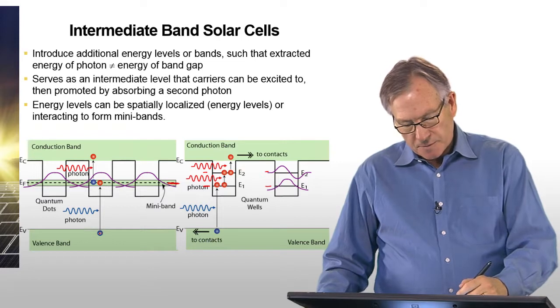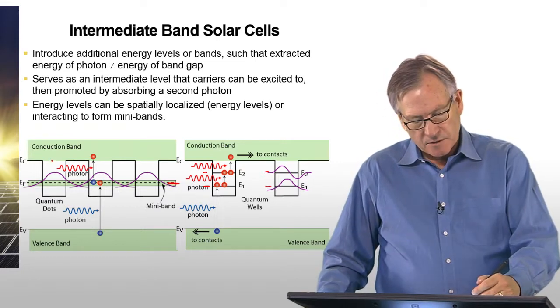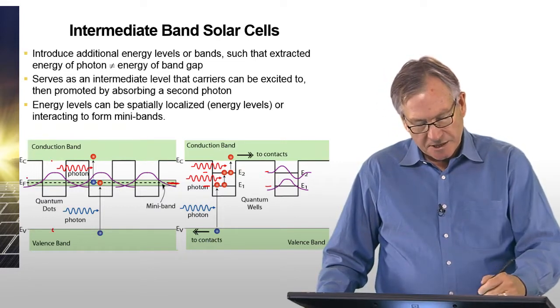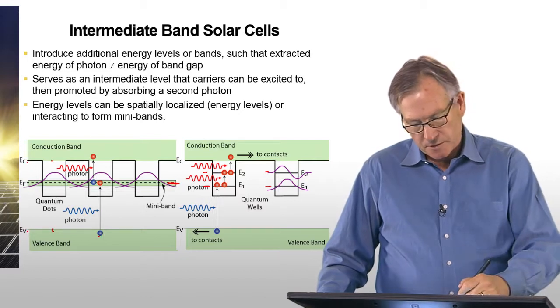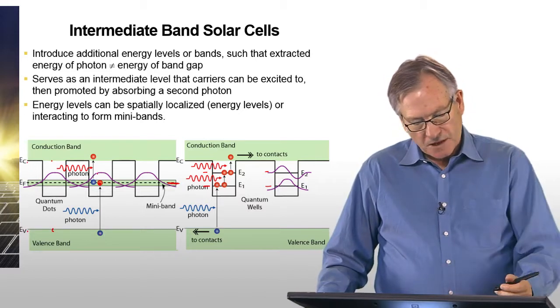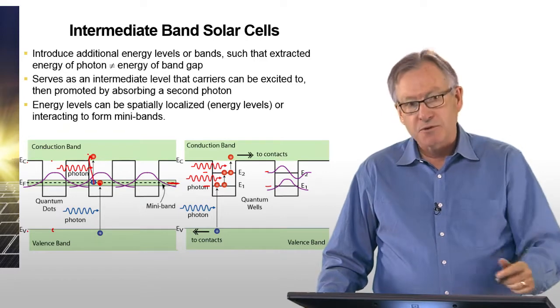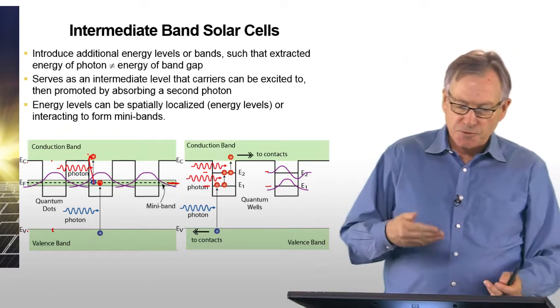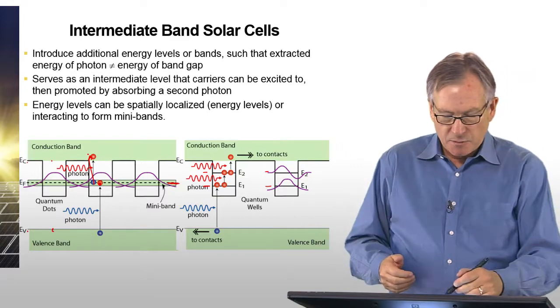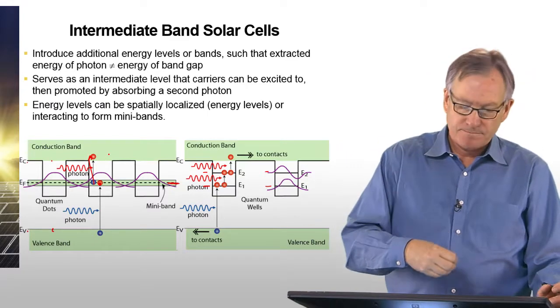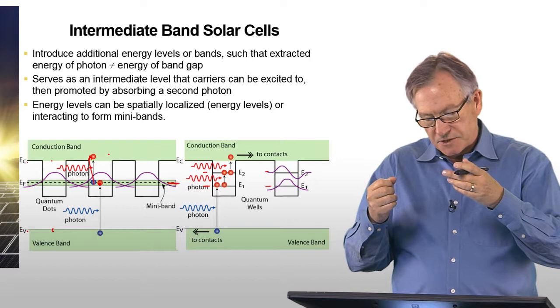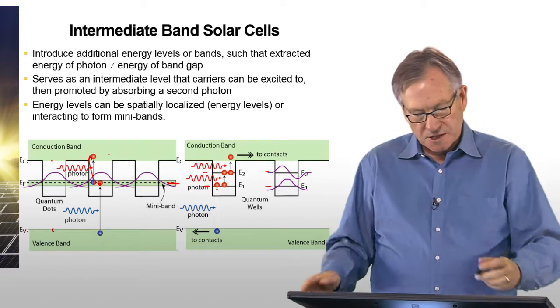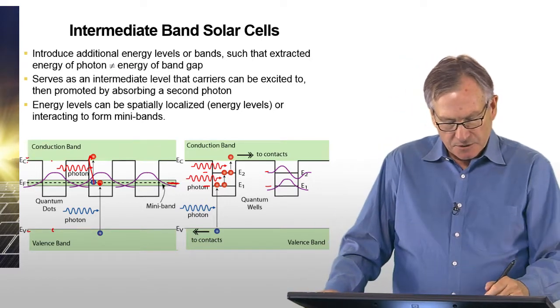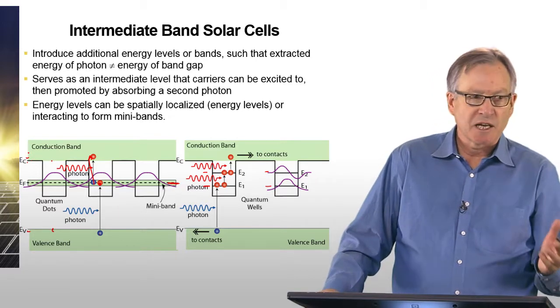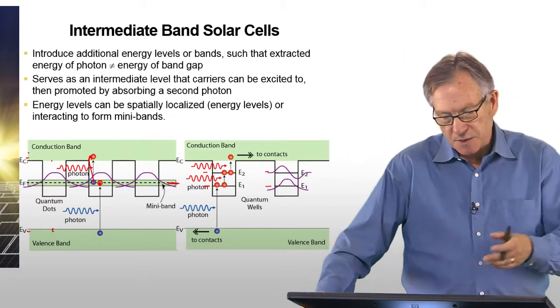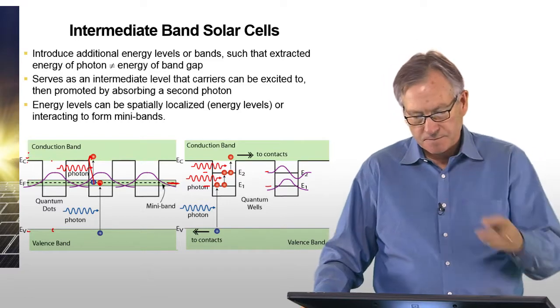In other words, as shown here, a photon with a photon energy less than the band gap between EC and EV of the host material can be promoted to this level, and then a second photon can be absorbed, promoting it to the conduction band. And so in this two-photon absorption process, you absorb photons below the band gap, but you generate electricity, or you produce a voltage that corresponds ideally to the valence and conduction band of the wide band gap material. So you get the same open circuit voltage, but a higher current essentially.